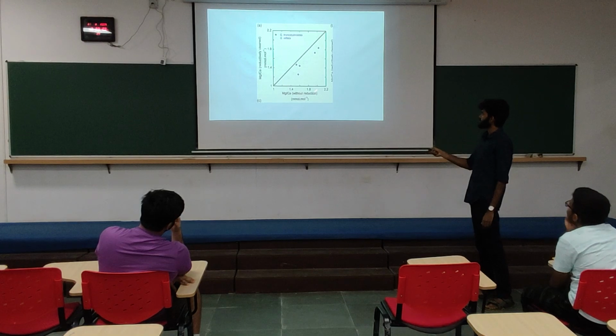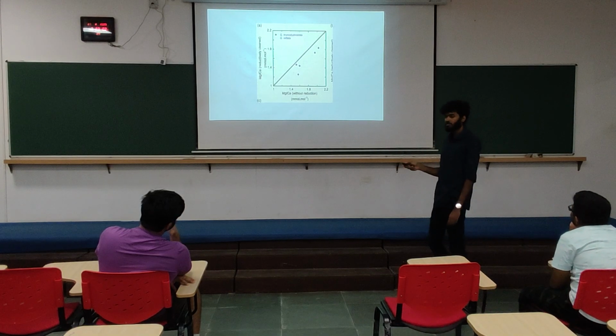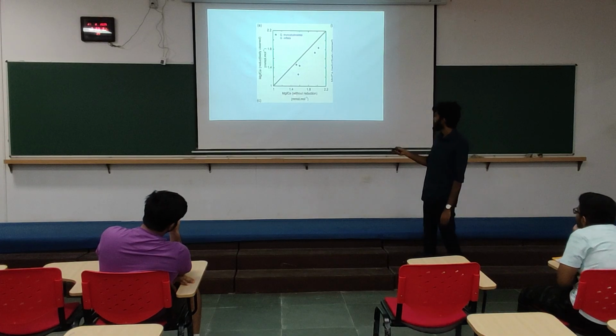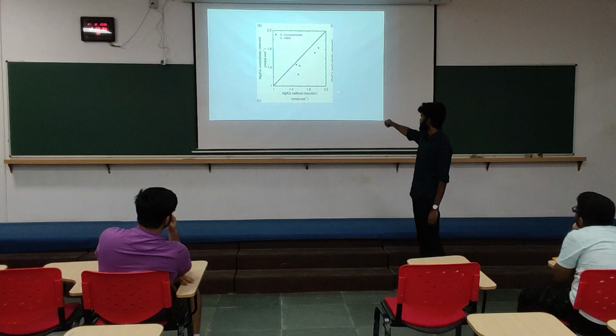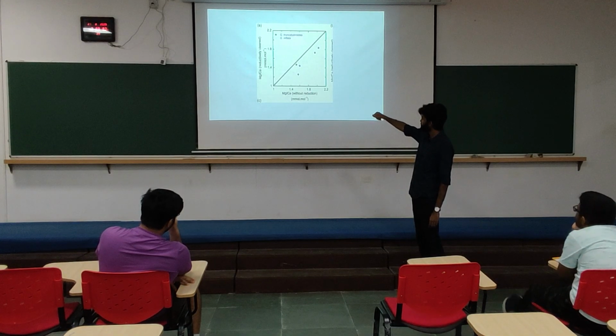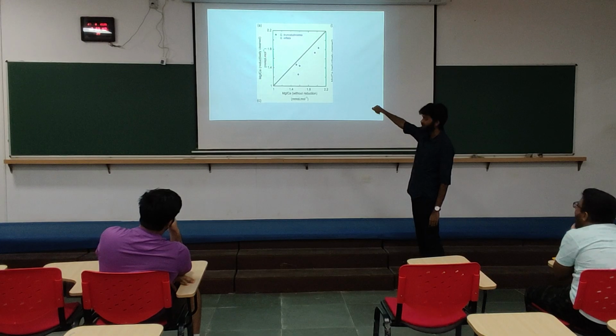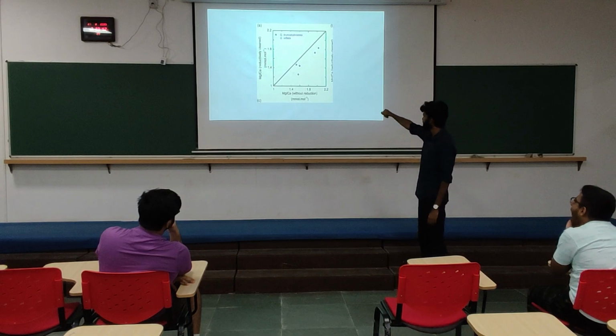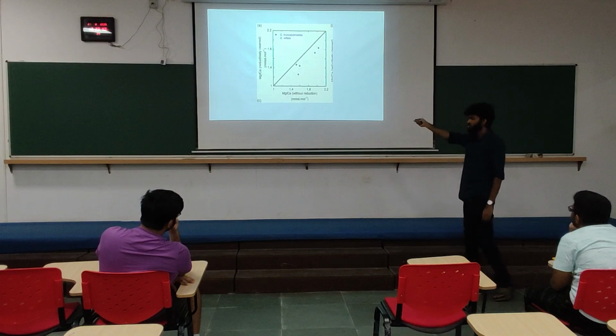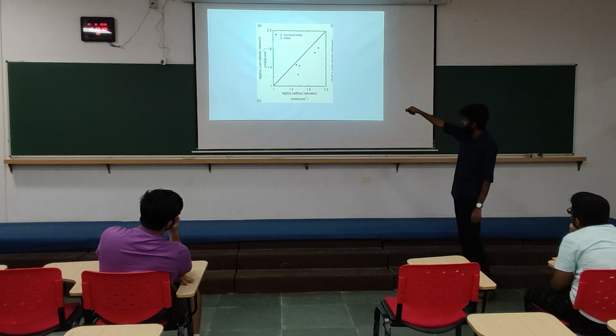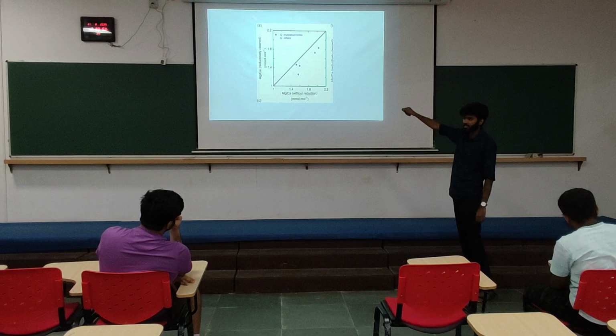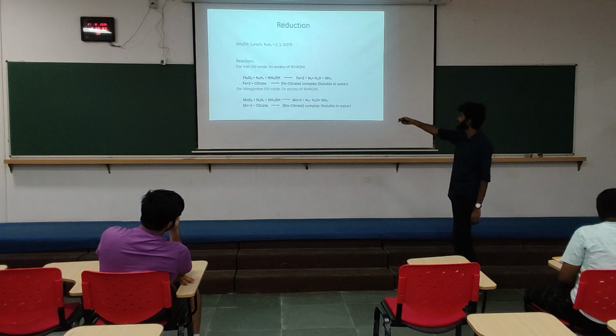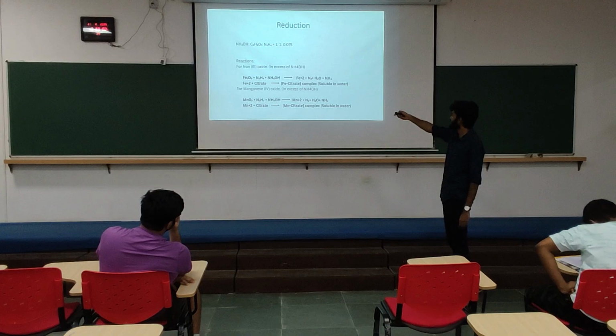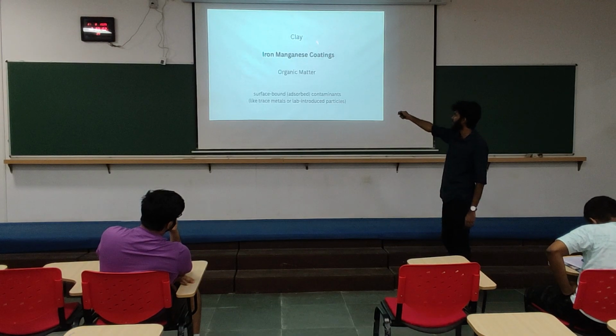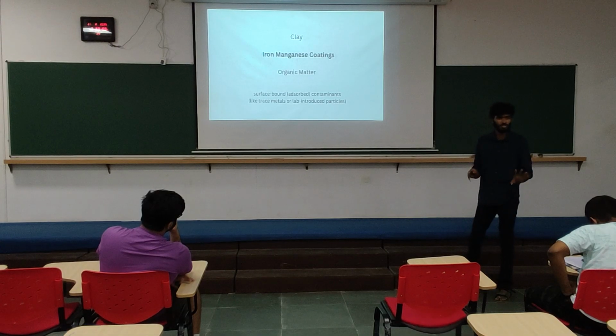Okay. Now this graph is actually showing us a problem that we face during the reduction step. This is the magnesium by calcium without reduction. This is the magnesium by calcium ratio after doing the reducing step. So we can see all the points are on this side of the graph. So what it means is the magnesium by calcium ratio is decreasing when we are doing the reductive cleaning. But if you see, I already told you this reduction method is used to remove the iron manganese layer, not the magnesium. So there is something wrong with this.